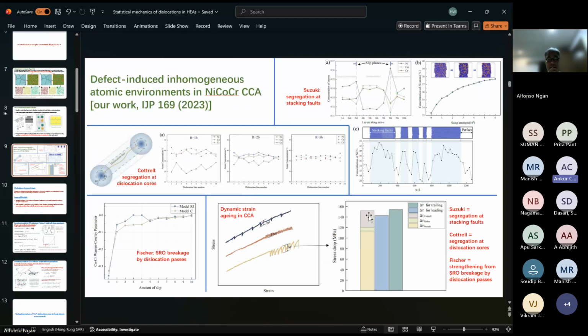Okay. One last query is about that. You mentioned, of course, here the nickel is sitting on the stacking fault plane, I guess. Yes. So for example, if you change the environment, of course, the segregating species will change, because this is more of a chemical interaction where you are stabilizing the HCP phase. Can you also comment on whether, if you are close to a grain boundary, there is a competing mechanism, because that one is more of an elastic interaction? Does this change your contributions from the Suzuki?